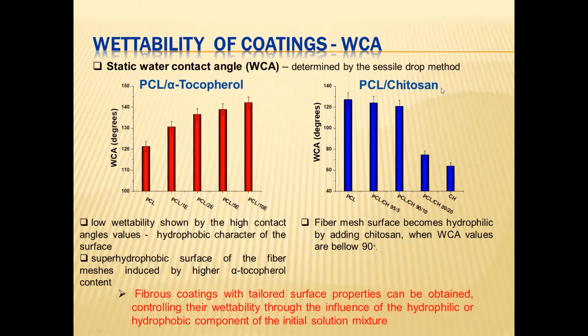For the PCL chitosan fiber meshes, the surface became hydrophilic by adding chitosan in composition. At 20% chitosan in composition, the water contact angle is already below 90 degrees. Therefore, fibrous coatings with tailored surface properties can be obtained, controlling the wettability through the influence of the hydrophilic or hydrophobic component in the solution mixture.